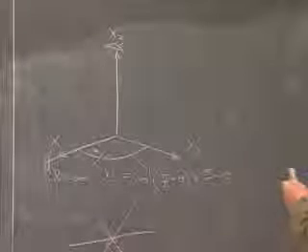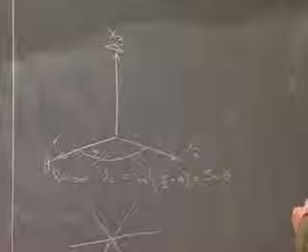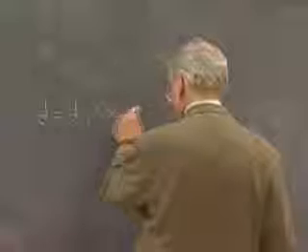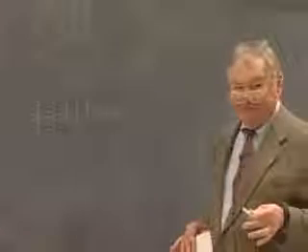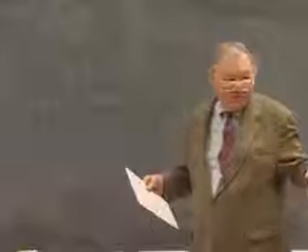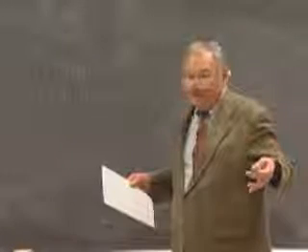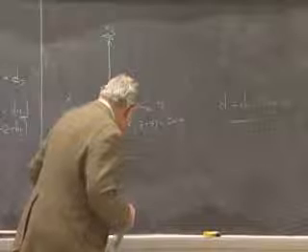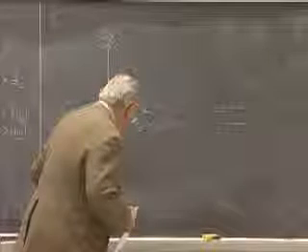So this identity, as you all know, I'm not telling you anything you don't already know, this is d equal to d11 times the cosine of 3 theta. Right? You knew that. Believe it or not, it is. It's one of these obscure trigonometric identities which wouldn't occur to you in a million years unless you go digging through some handbooks. So this is rather astonishingly simple. It's simply a cosine function, but the interesting thing is it goes as a function of 3 theta. So this goes through one cycle between a pair of adjacent twofold axes.